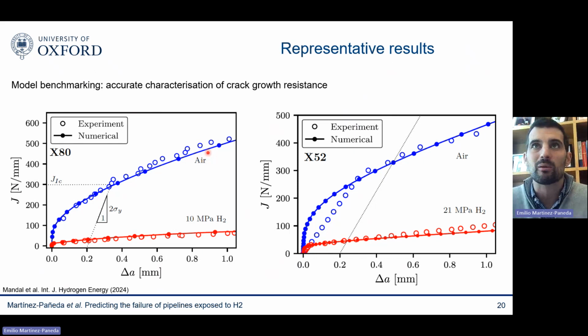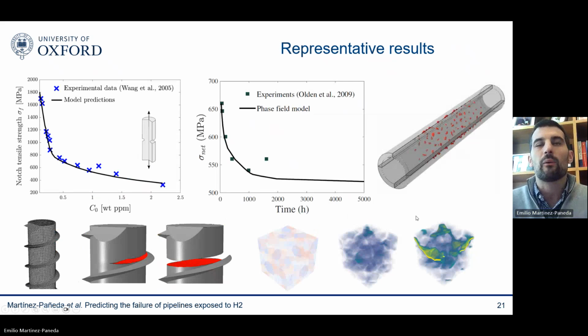And again, with no fitting parameters whatsoever, there's no calibration involved here. And you can see that we predict very well what's happening in air. And then we introduce hydrogen into our samples by using Sieverts' law and putting an appropriate boundary condition, and we capture very nicely what comes out of it. And we have also tested these models across a wide range of materials. This is a comparison for high-strength steels. This is for duplex stainless steels. So everything here, you can see that we get a very good agreement with experiment.